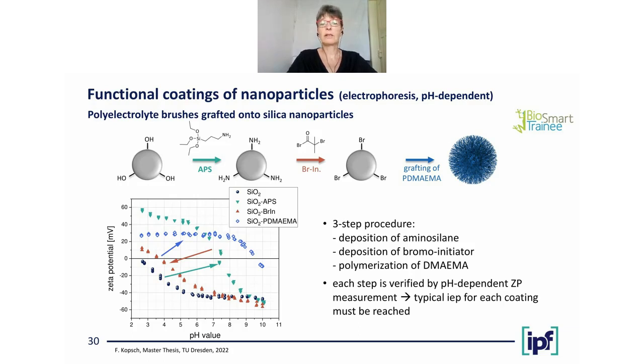Another field of our work is the functional coating of nanoparticles. So we use different nanoparticles, cover them with polymers, in this case a so-called polymer brush. That means the polymer chains are attached at one end to the particle surface and extend freely into the solution. We normally start with a particle, in this case a small silica nanoparticle. We apply an aminosilane to create amino groups to the surface. Then a bromo initiator is attached to these amino groups. And in the end, from these bromine groups, a polymerization reaction starts that results in these polymer chains, this so-called polymer brush.